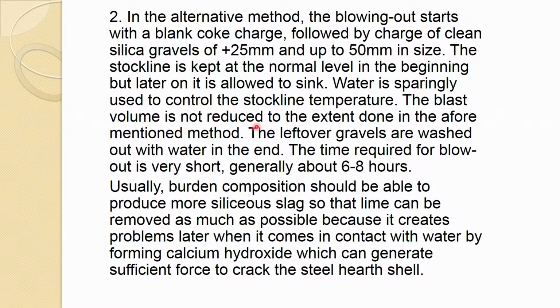The blast volume is not reduced to the extent done in the previous method. So, in the previous method we reduced the blast volume quite a lot, but in this one you do not do that much. The leftover gravels are washed out with water in the end. The time required to blow out is very short, generally about 6 to 8 hours in this case. So, this is a very quick method, and usually burden composition should be able to produce more siliceous slag, because anyway you are putting silica gravels.